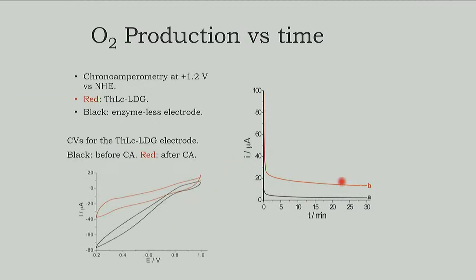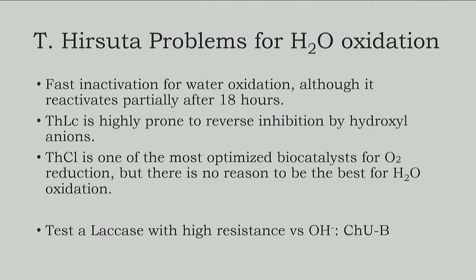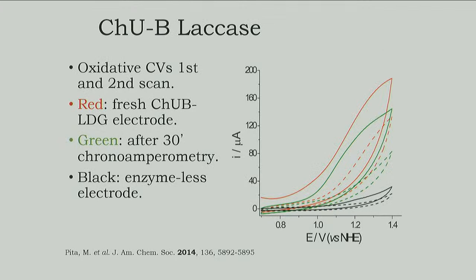Again, we can see here, after this chronoamperometry, this is the natural response of the enzyme before and after, so the activity was going down. So this enzyme we are naturally used to, because it's the best one for oxygen reduction, was not very good for water oxidation. It was inactivated and the reversibility was not very high, and then we decided to go again to our collaborator and ask for a mutant enzyme. Maybe if it has a higher resistance, it was going to perform better, and it was like that.